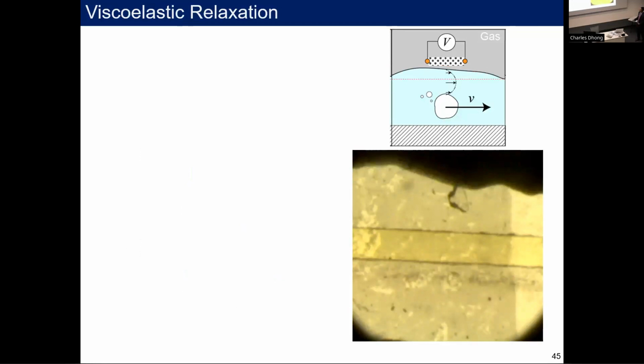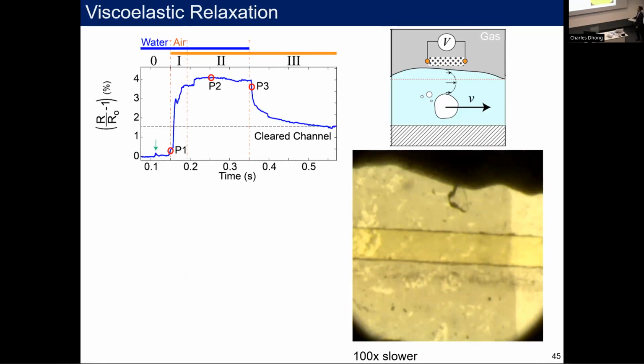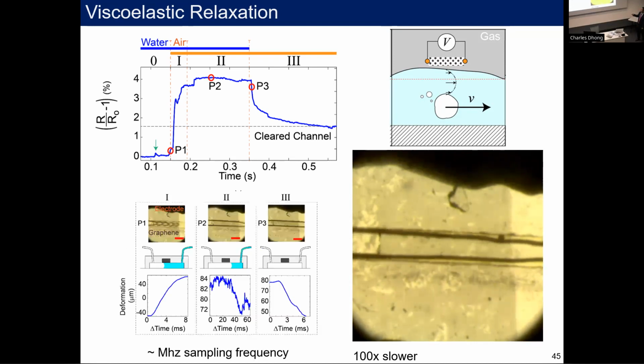This is the last way I'll show it, and this is the way we actually use this currently. So this is a bubble clearing through the channel. It's filled with liquid, and then I shoot air through it. When that happens, you actually get a very strong signal on the sensor. And what you're seeing here is this bubble transiting across the channel.